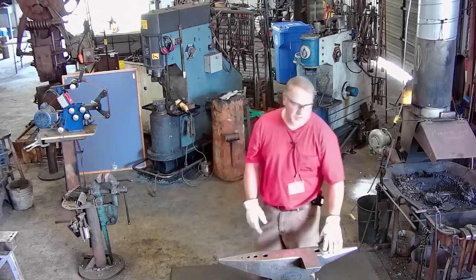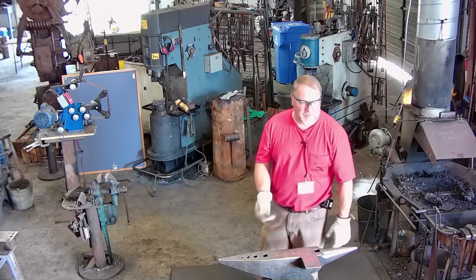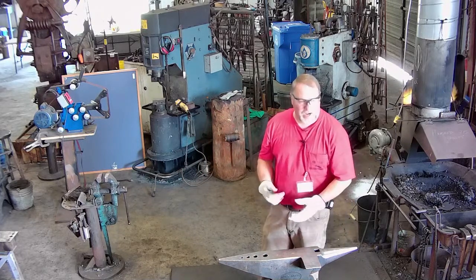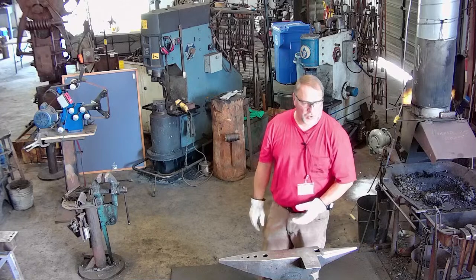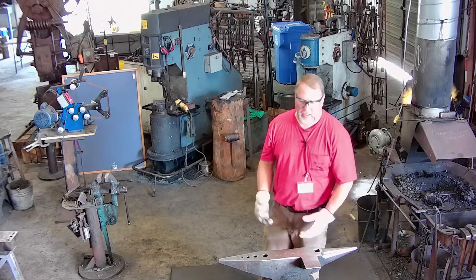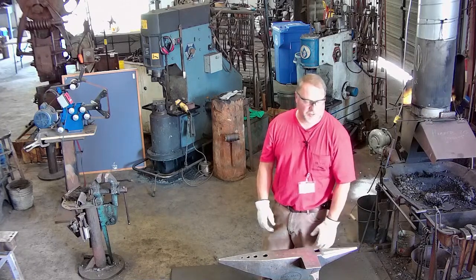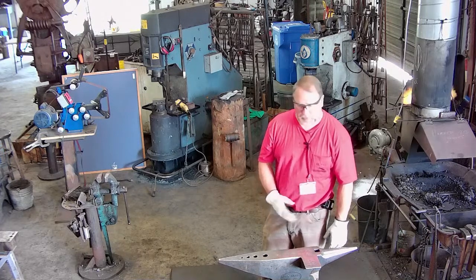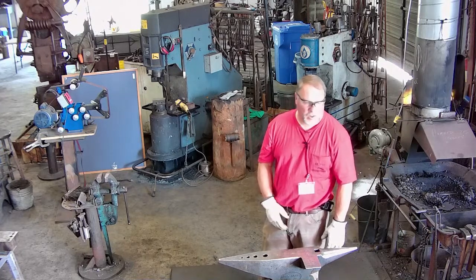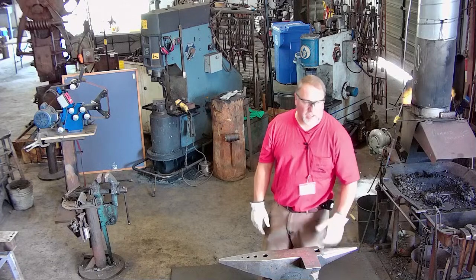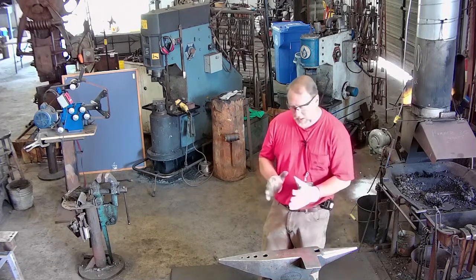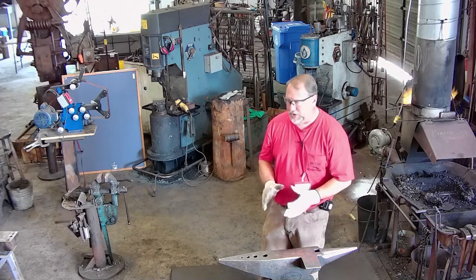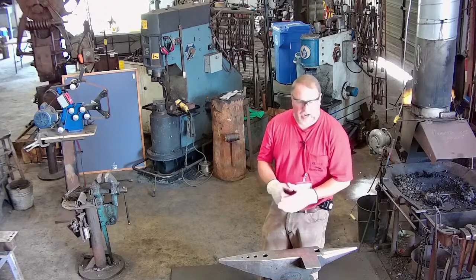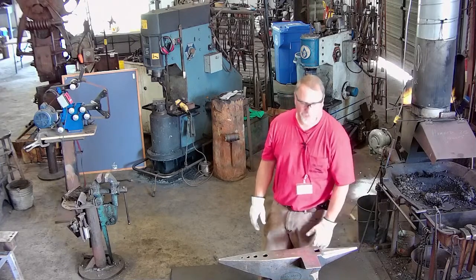The question was, if I have a shear or a delam on my billet, is there a way to fix it in process or while you're forging it? And the best results I've had is either split it in half at that shear, or abandon it and go on and make another billet, because you'll do your best to get a good solid forge weld in there, but it may not show up till you're doing your final grinding.